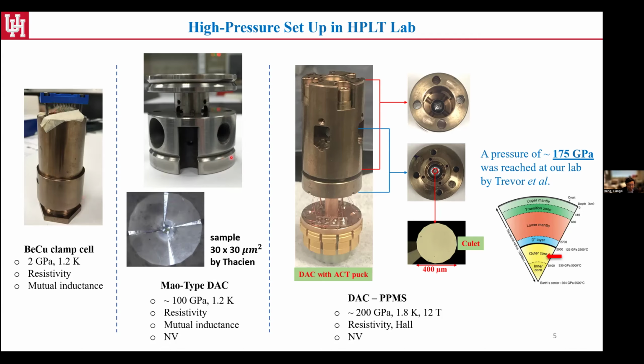Definitely, if we want to increase the pressure range, we have to move to the diamond anvil cell. That's the very famous Mao-type DAC, which can normally reach 100 GPa, depending on the diamond culet we use. Here I'm showing one, but it definitely needs more training and a careful, very handy student to take care of it. One of our students was able to put the four leads by hand on 30 by 30 micrometer samples. It's very beautifully done, and they're not touching each other. I'm very proud of this. There's also another beryllium copper diamond anvil cell that can adapt to our PPMS, so we can do more measurements under magnetic field and with better temperature control. Recently, in one of the experiments studying Kagome materials, we were able to reach around 175 GPa. It's also worth mentioning that the NV technique has now been intensely coupled into the diamond anvil cell, which gives another strong aspect to these high pressure studies.